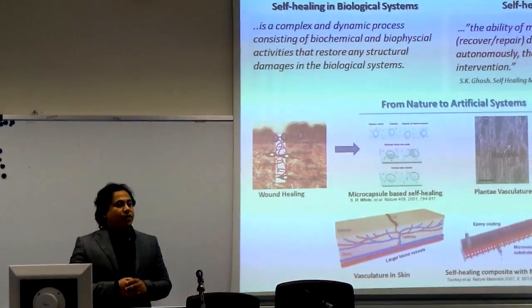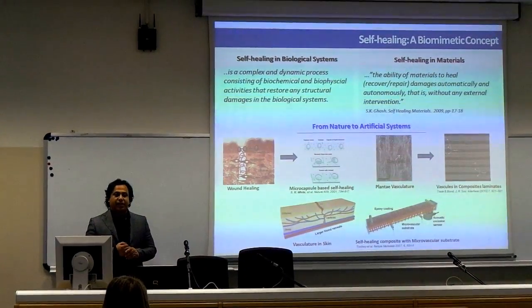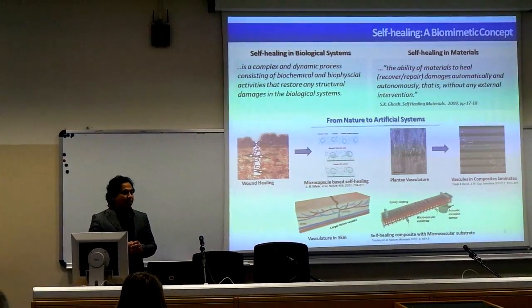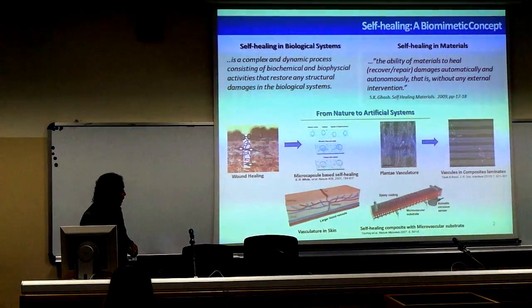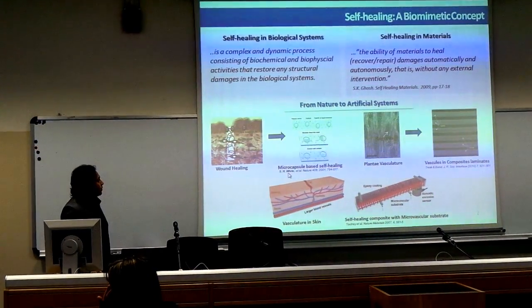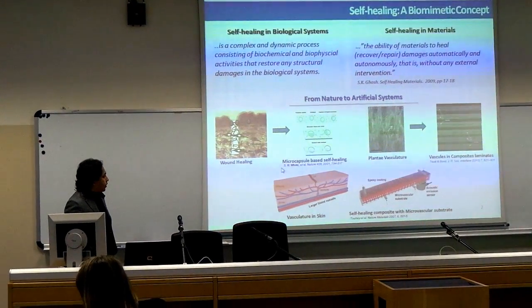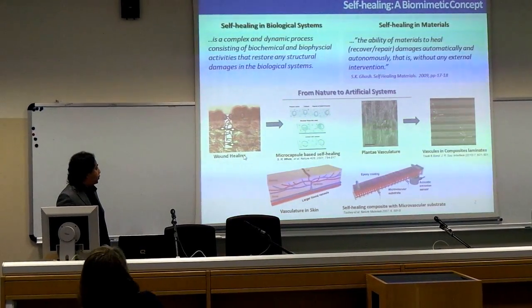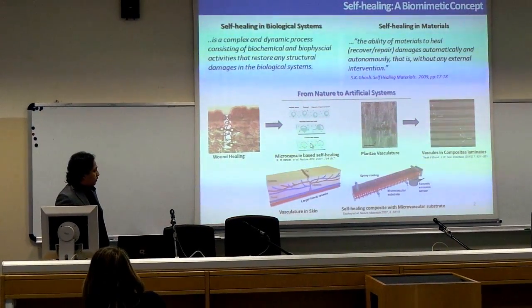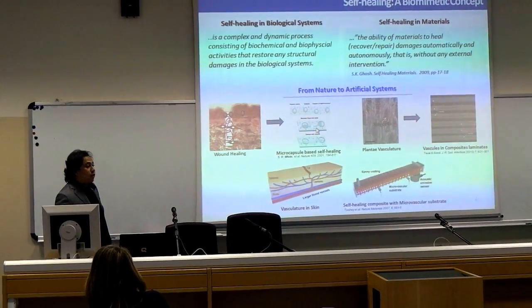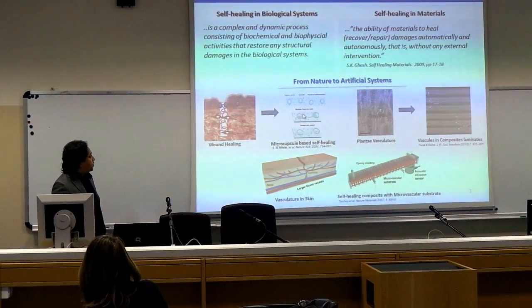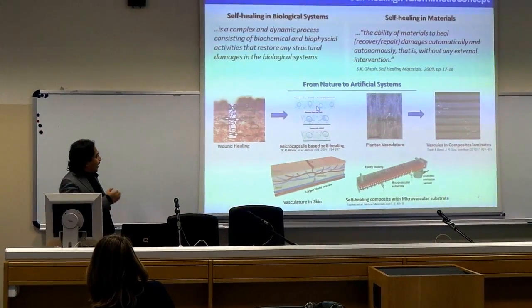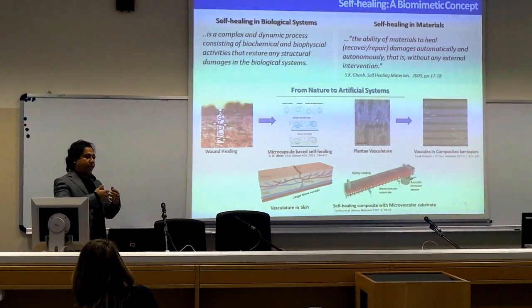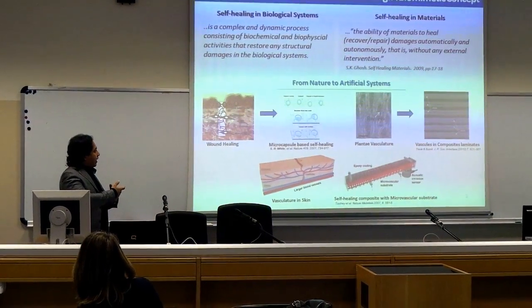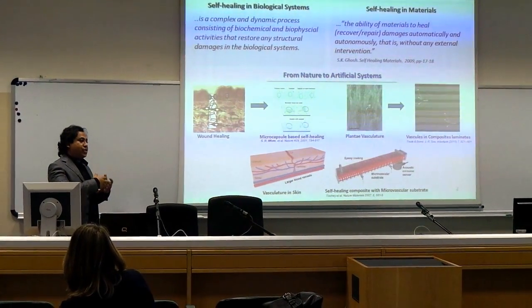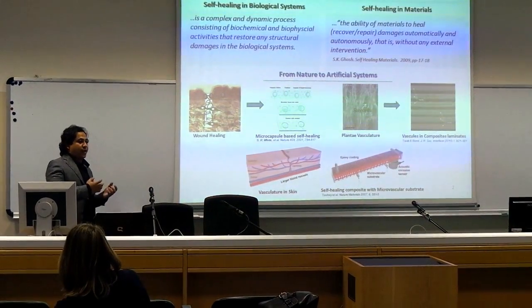Over the past 2 decades, there have been a lot of research works in the scientific community to develop such materials with healing ability. For example, here you can see that Professor Scott White in 2001 first published a work where they wanted to mimic the wound healing mechanism of human skin tissue to develop epoxy-based composites, where they embedded microcapsules containing healing agents and dispersed the catalyst inside the matrix. Upon crack initiation, if the crack also breaks the microcapsule, it will release the healing agent, and when it comes in contact with the catalyst, it will initiate the polymerization at the crack, and this way they self-heal.